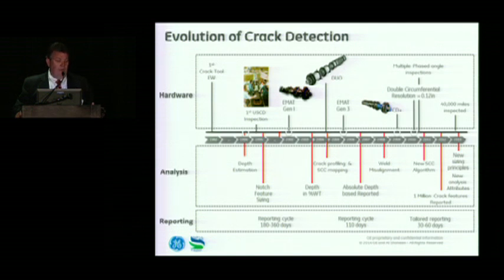What we then realized was that people are asking us to find two types of cracks, single cracks and crack fields, and just find them. We'll deal with the rest of it. And so we started doing that. And then we tried to get clever and make it into a sizing tool, and we realized that the sizing capability of that tool was limited. It was a threshold of 25% of the wall thickness, plus or minus 25%. So you either had a 75% crack or nothing, really. But that's what it was back then.